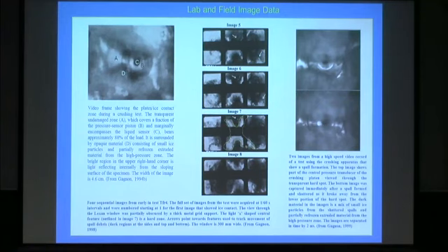This was from the ice island experiments, that X shape that formed, the spallation that occurred there. And this is just an example of a before and after shot for a spall that occurred during these tests. So you see a contact zone here, hard zone region, and shattered or crushed ice around that. And then a spall occurs in this region, so a portion of that contact area shatters.